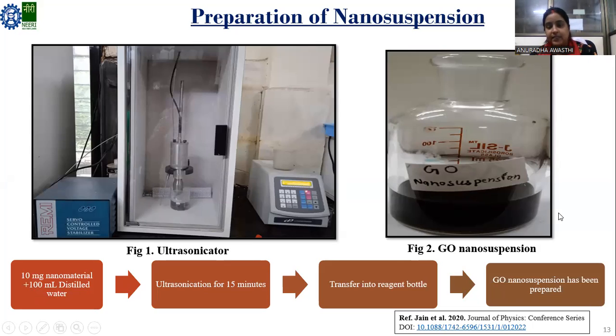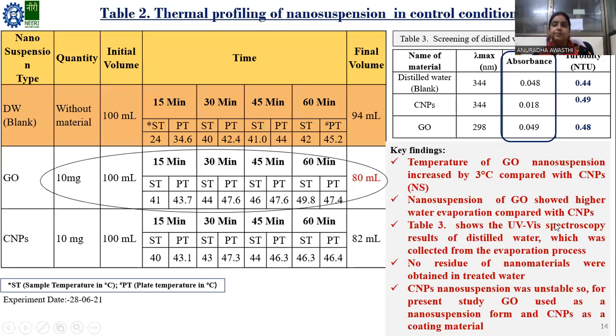I have done the DLS and zeta potential studies to understand the basic phenomena and the characteristics of this GO nano suspension. After preparing, I did the thermal profiling of the GO nano suspension. As you can see, the GO nano suspension evaporated more water as compared to the CNP and blank system. What I have concluded, the temperature of the GO nano suspension increased by 3 degrees as compared with the CNP nano suspension. The nano suspension of GO showed higher water evaporation compared to the CNP.